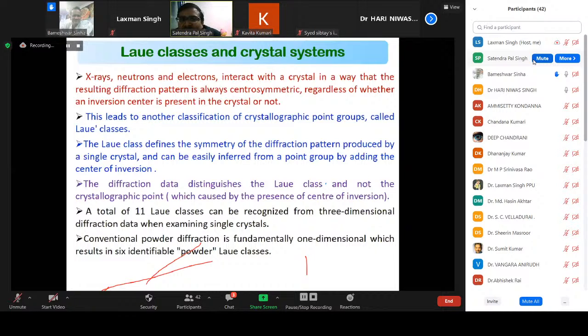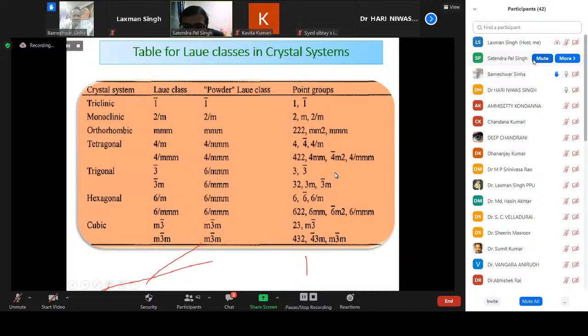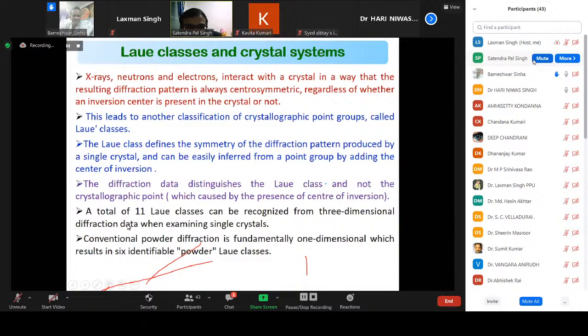So all these X-ray, neutron, and electron diffractions give a centrosymmetric diffraction pattern, regardless of whether the structure is centrosymmetric or not. This phenomenon leads to a crystallographic point group called the Laue class. The Laue class defines the symmetry of the diffraction pattern produced by a single crystal and can be easily inferred from a point group by adding a center of inversion. So in total, there are 11 Laue classes.